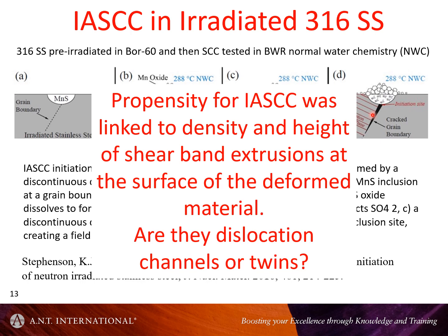But if you've got a whole bunch of dislocations, one on top of the other, pileup like this, they're going to cancel. The strain field is going to cancel. So the broader strain field is not going to be realized. So again, this is kind of like a speculative mechanism, which frankly I'm not too keen on.